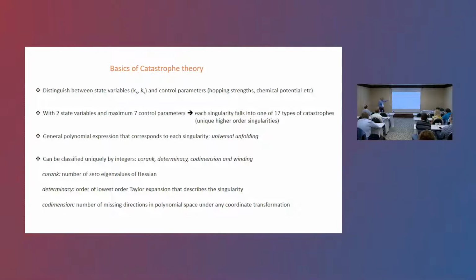So this is not important, but it's important to convey the message of how we do things. We distinguish between state variables, which in our two-dimensional systems are kx, ky, and control parameters, which are the hopping strength, chemical potential, magnetic field, etc. With the usual 2 state variables in 2D and a maximum of 7 control parameters, we have 17 types of catastrophes in 2D, no more, no less. This is exactly the number of different singularities that we can have, and each one is a unique higher order singularity.